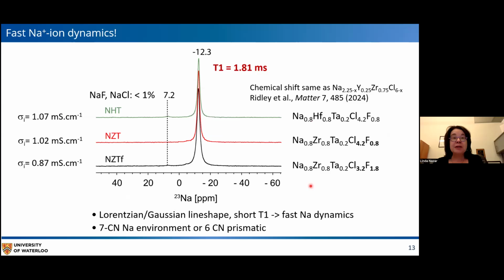postdoc, Young Chui. And of all of these materials we've looked at, this is the parent material, which I mentioned, the NZT. We have this more highly fluorinated version, which we obtain by reacting the parent with the tantalum fluoride. And we've also done hafnium just as a proof of concept or a check on the system. So you can see that the conductivities are all fairly similar, and what's surprising is that this very highly fluorinated material has a conductivity really quite not far off that of the less fluorinated material.